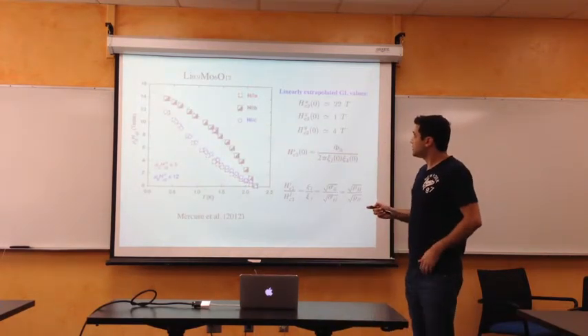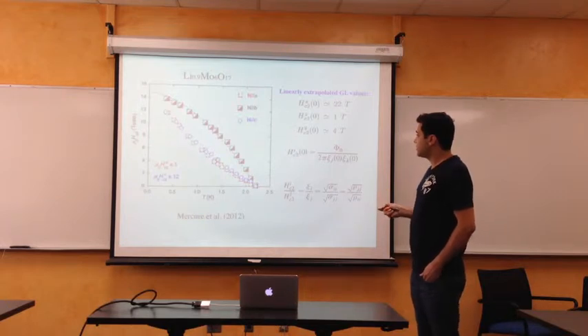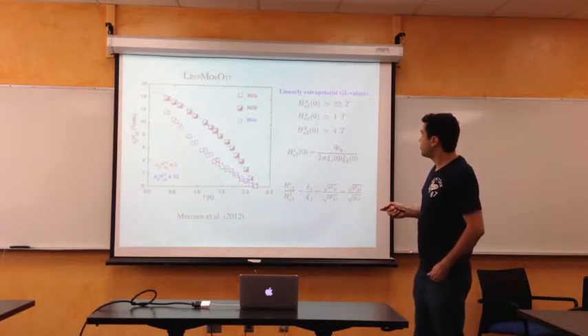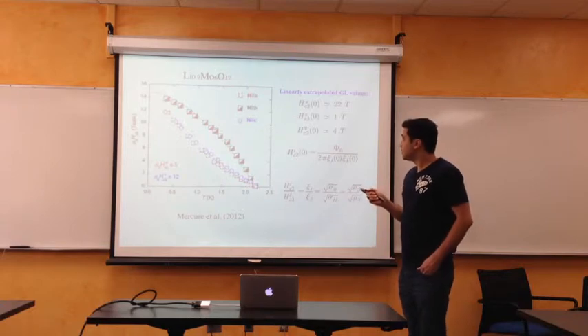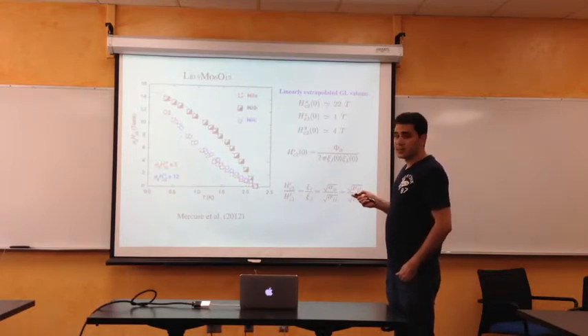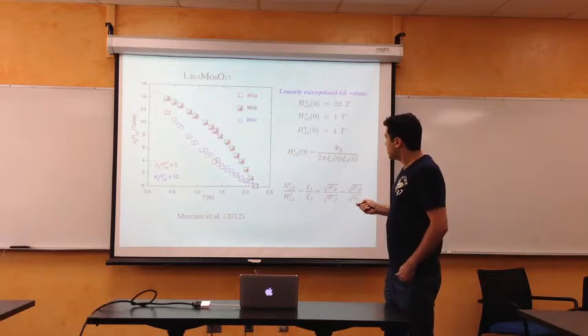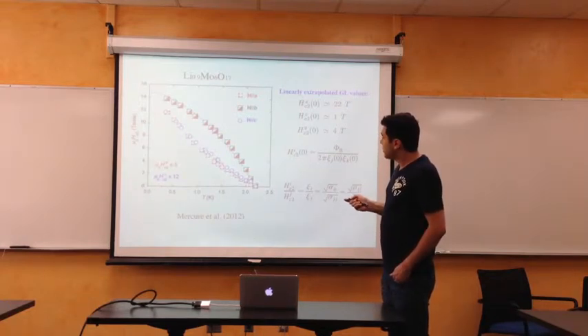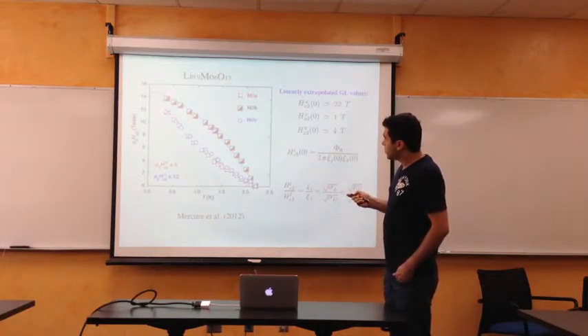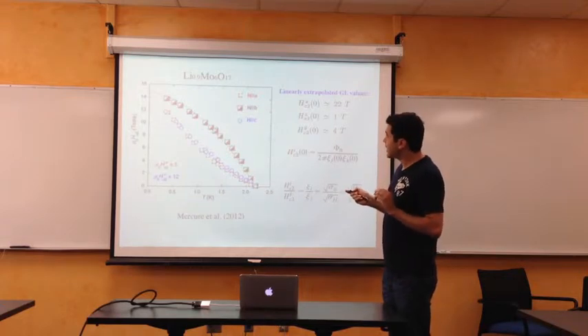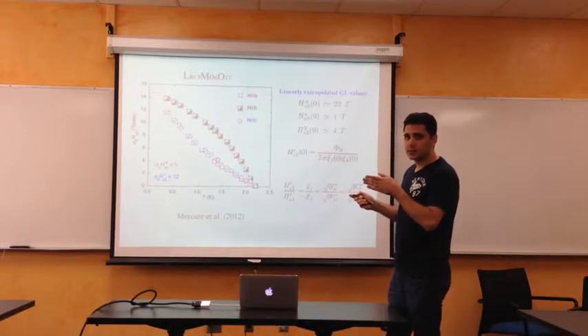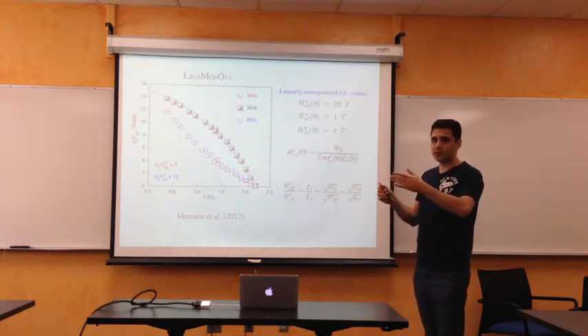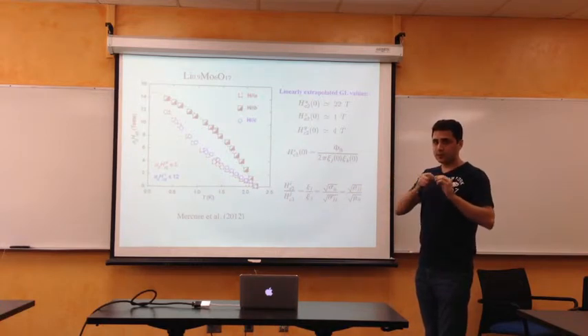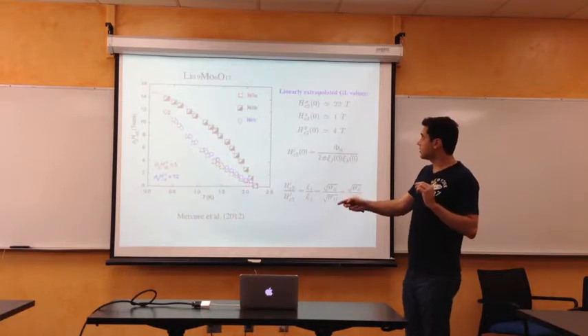So this is a magnetic field versus temperature diagram for this purple bronze. We see here a very puzzling situation because as we approach 0 Kelvin, all the fields along all the crystallographic axes tend to saturate, and in particular the field parallel to the most conducting axis. This is a quasi one-dimensional crystal; we take the x-axis to be the most conducting axis.